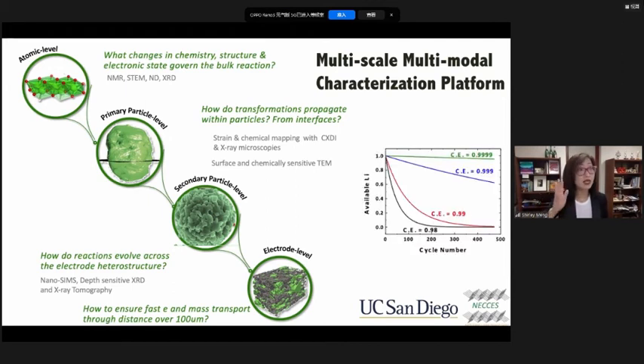Because if you have any inefficiency that causes the loss of lithium, even 1% can cause a very detrimental effect on your battery's cycle life. And this graph very simply shows the importance of Coulombic efficiencies. When we have a battery that can last for 1,000 cycles, the lithium shuttling between the cathode and anode is highly efficient. So if we are building characterization techniques and trying to decipher where the degradation happens, this job is very difficult because the change is indeed very, very subtle. We're trying to detect less than 0.1% of the degradation phenomena.